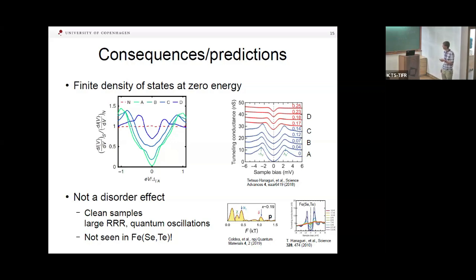And that property, just to rule out other explanations, should not be a disorder effect because the samples are quite clean. They have quite large residual resistance. They show quantum oscillations. So the simple disorder filling effect might not be the explanation. And as a side effect, there is a sister compound, iron selenium tellurium, where you replace the selenium with tellurium. Then the same effect is actually not seen.